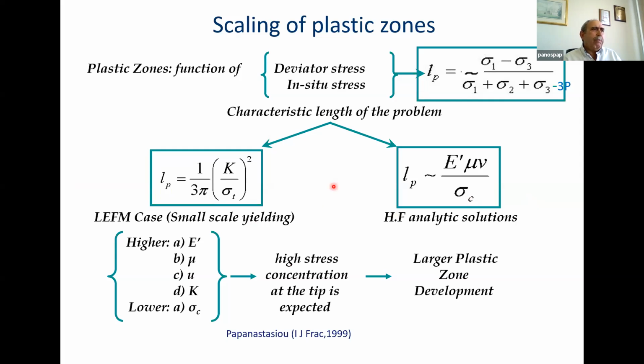Now, how important is plasticity? It depends on the scale of the plastic zones. If the plastic zones are small, plasticity will not be important. So we attempted to scale the plastic zone to see which parameters it will depend on. And of course, the first parameter we found is the deviator of the stresses, the difference between the stress along the propagation direction minus the stress normal to the fracture plane, the closure stress, as you can see.